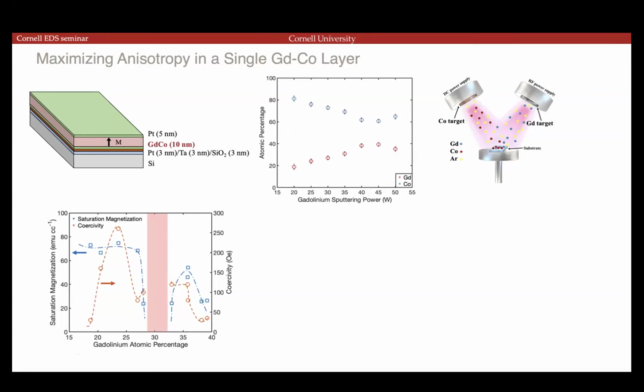So in a ferrimagnet, there's a certain temperature at which the two moments will perfectly cancel and you get zero net magnetization. We call that the compensation temperature. You can also get a compensation with composition: gadolinium and cobalt are what we call sublattices that are oppositely magnetized, and each one is contributing a certain amount of magnetization. As we vary the composition, we should get to a certain composition where the two are oppositely magnetized and equal in content, so there's no net magnetization. And that's observed in this graph where we plot the saturation magnetization as a function of gadolinium content. There's a certain point at which the magnetization drops to 0.